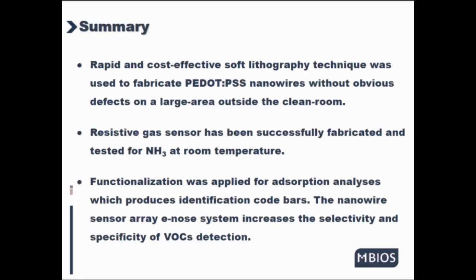And at last, let's make a summary. A repeatable and cost-effective soft lithography technique was used to fabricate PEDOT:PSS nanowires without obvious defects on a large area outside the clean room. And second, the resistive gas sensor has been successfully fabricated and tested for ammonia at room temperature. And third, functionalization was applied for adsorption analyses, which produced identification code bars. The nanowire sensor array e-nose system increased the selectivity and specificity of VOC detection.